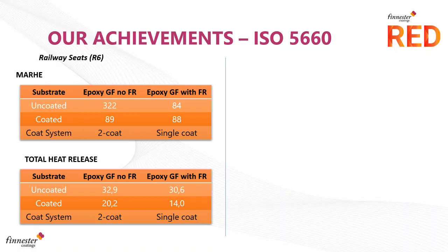Alternatively, if you're taking an epoxy glass fiber that already contains some fire retardancy, some fire performance that is meeting a hazard level 2 application, on that occasion, instead of applying a two-coat system, we put a single-coat system on. We don't want to be increasing the fire load with our coating technology. We want to keep it down to a minimum application and still retain the hazard level 2. That provides obviously the decorative and outdoor protective requirements for the application. And as you can see, in combination with the improvements in this MARHE number, we can also reduce the total heat release by adding our coatings onto standard epoxy glass fibers.